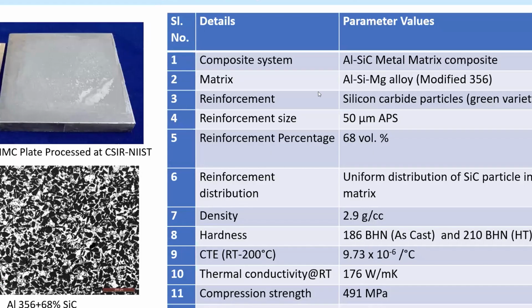And one of the typical experiments is that this SiC particle has high thermal conductivity. Because of this, in an aluminum silicon alloy, we had added almost 68% of silicon carbide and infiltrated the material. And we observed that the hardness is around 210 BHN. One of the requirements in an electronic thermal management system is low CTE and high thermal conductivity. So we observed that CTE is very low. Normal aluminum alloys have more than 20 ppm per degree C, but this one has very low CTE, and thermal conductivity is 176, with good strength and modulus.